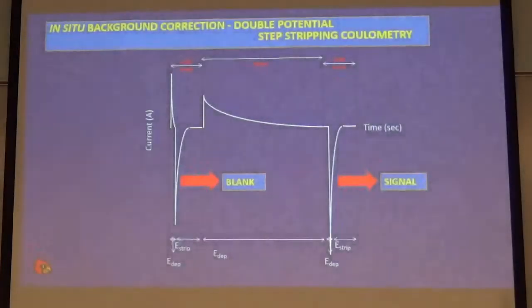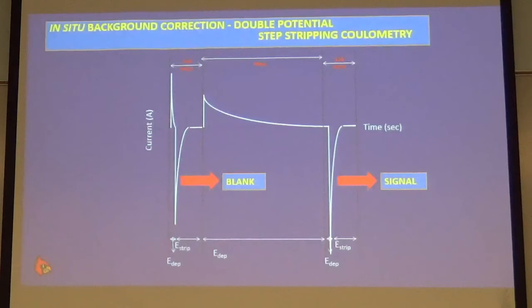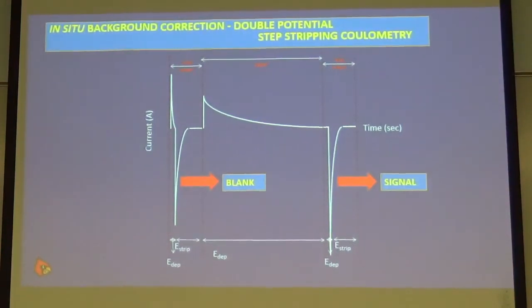All right, now, the actual measurement step sequence that we use is a little bit more complicated. Ideally, in the field, we would like to do an in situ background correction. Now, for the previous data, to get that blue line, the graduate student running the experiment had to fill the cell up with a blank solution, get the blue line, then fill the cell up with the analyte solution, and get the red line. Two steps, with a lot of pumping and movement going on. You don't want to have to do that in the field. You want to do that background correction in situ.